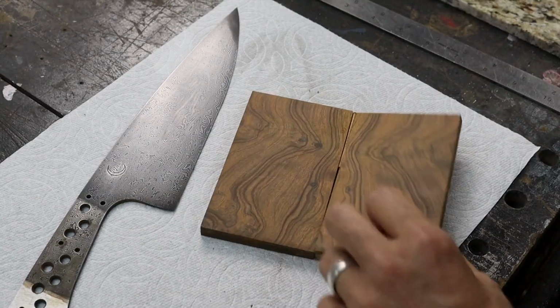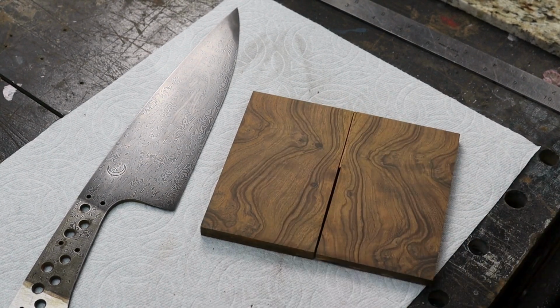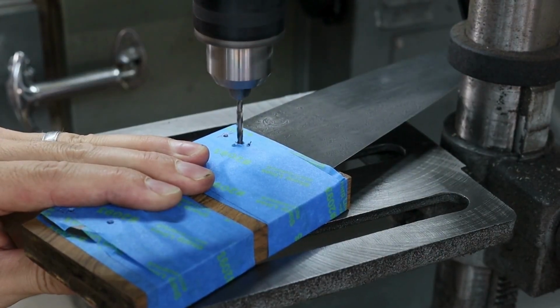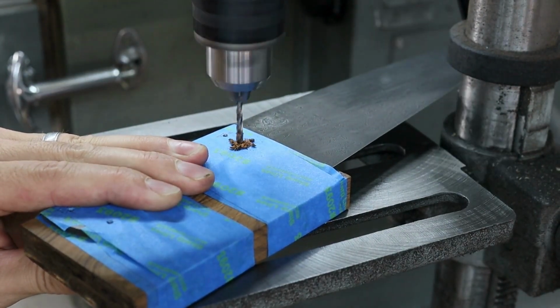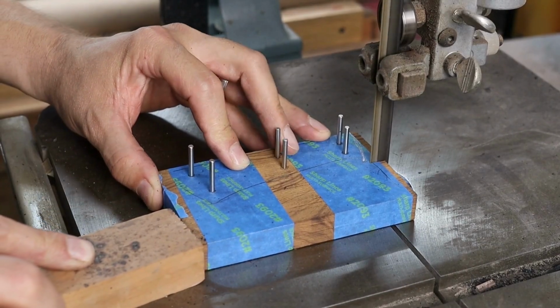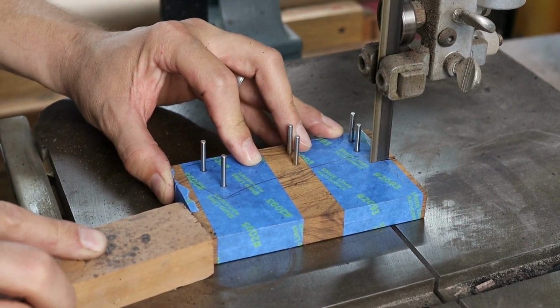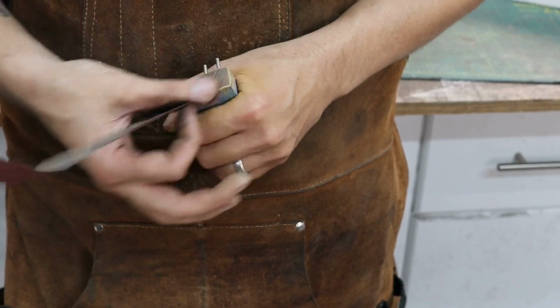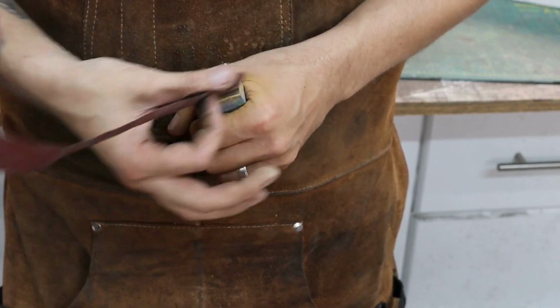I etched these knives for 3 5-minute cycles in ferric chloride and sanded with 2500 grit sandpaper between etches. I finished it off with about a 2-hour soak in coffee. Sunshine jewelry polishing cloths work great for removing the excess oxides once the Damascus is etched and finished.